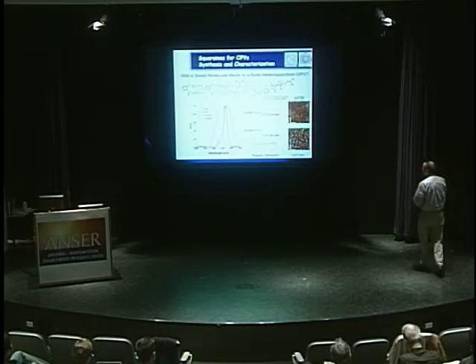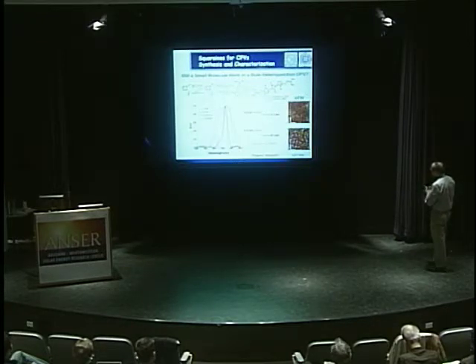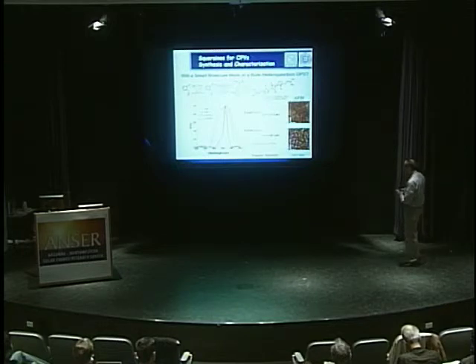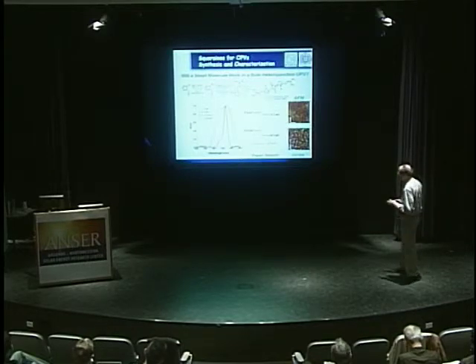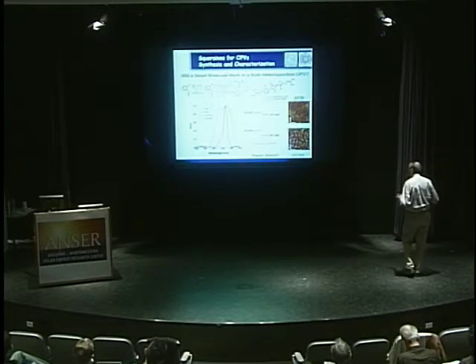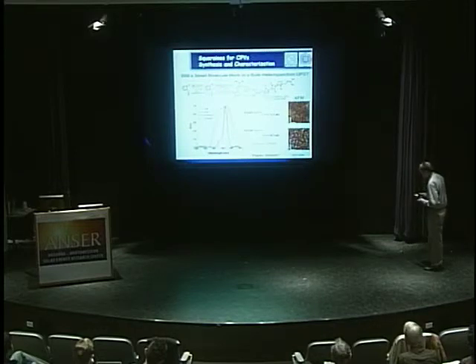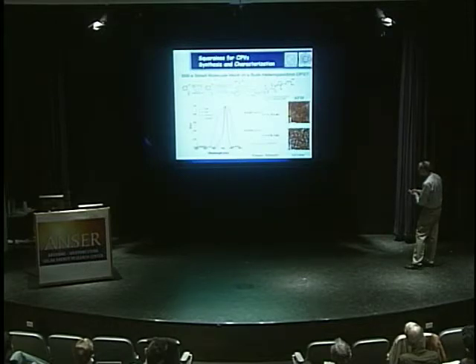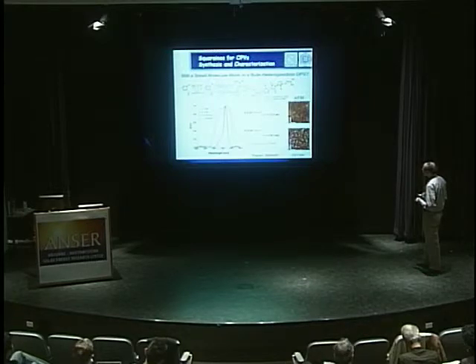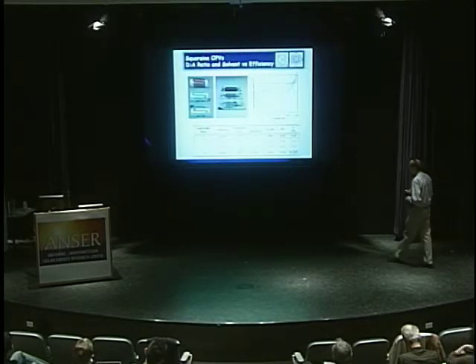So here's a collaboration with the Pagani group in Milano, and Giorgio's group has been making a number of squaraines, and one of the things that struck them was the optical absorption, especially as a film, is very, very broad, very large extinction coefficients, just where you want it. You can make, and the energy levels versus PCBM. In principle, we ought to get a really nice open circuit voltage. So let's look at some first generation cells with PCBM.